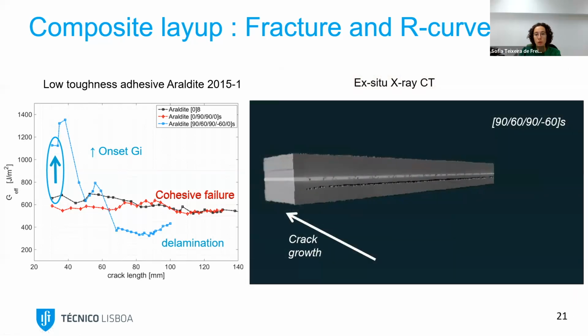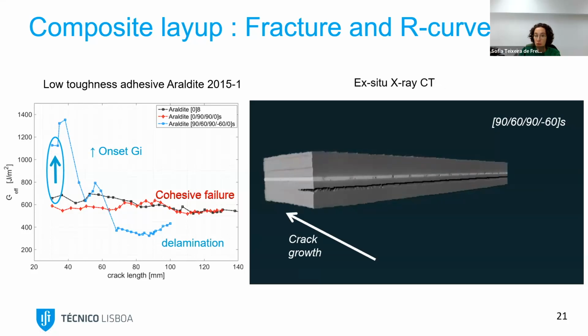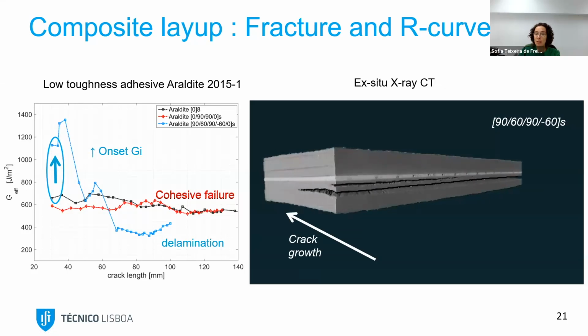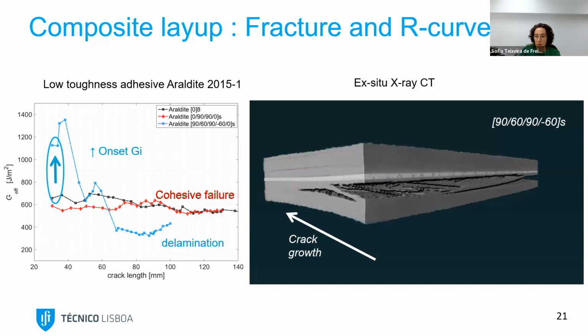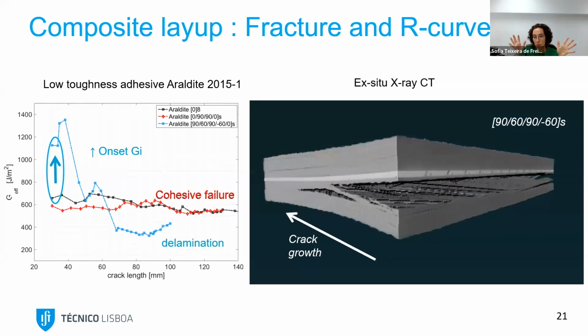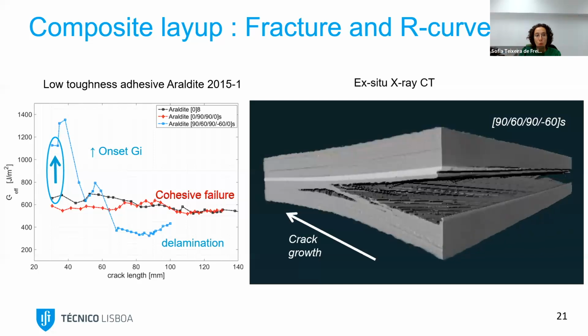So indeed, what we learned is that if we have a lot of fracture surfaces, so if we manage to dissipate the energy that we are imposing in the specimen to several fracture surfaces and several crack fronts, we can indeed increase the energy that is necessary to increase a crack.